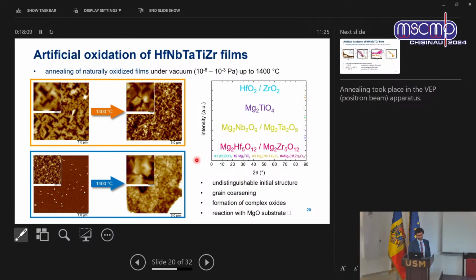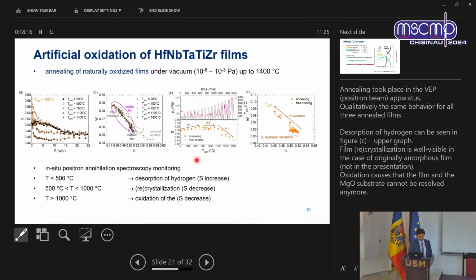But still, we could monitor the changes during this annealing, again, by positron spectroscopy, and it is well visible here in the first picture that even at the 400 degrees Celsius, we still have the magnesium oxide substrate. It's still intact, so it doesn't react at these lower temperatures, but at the surface regions, at these low implantation energies, it's already changing. So first, it reacts with the oxygen from the top, then it reacts with the oxygen from the bottom. So the magnesium oxide, yes, it is a problem if you want to post-process your films, but it will not ultimately save you from the oxidation problem.